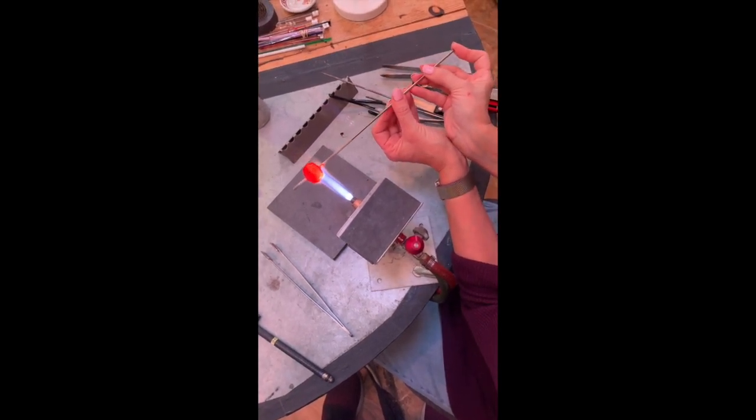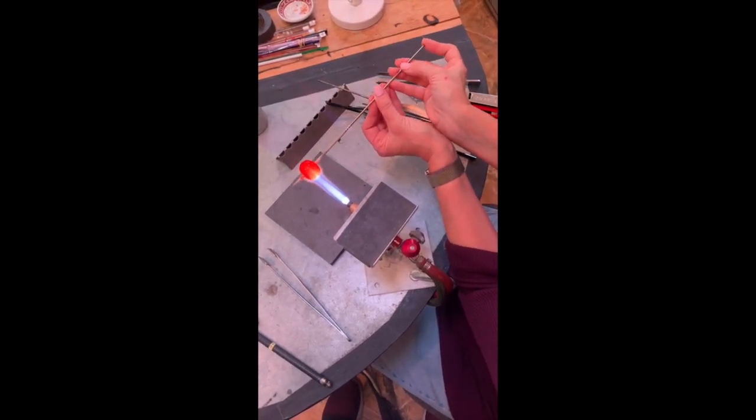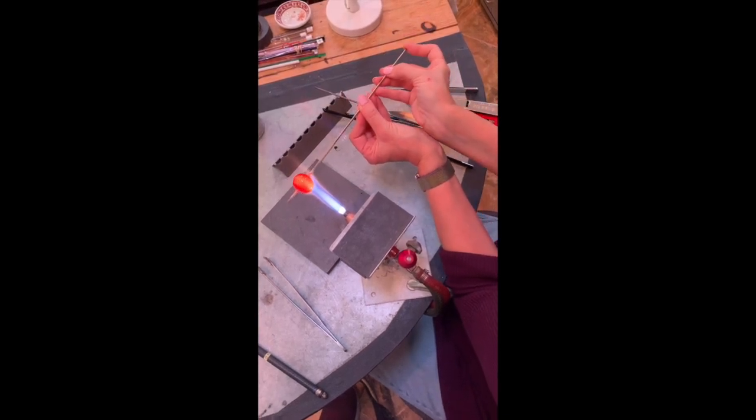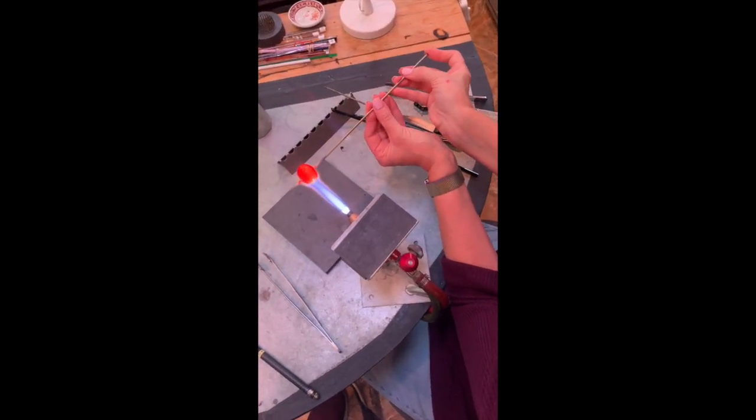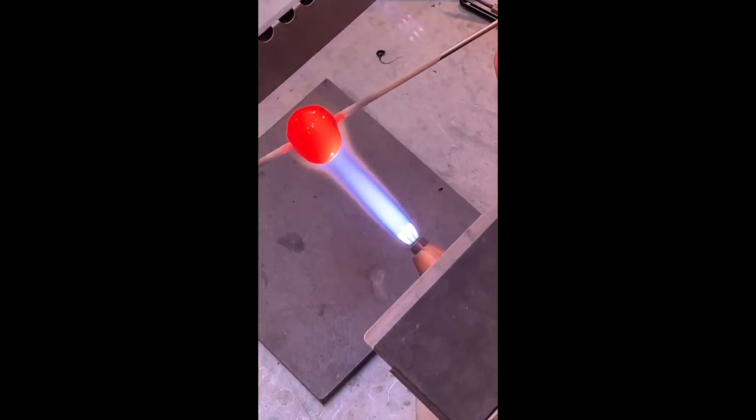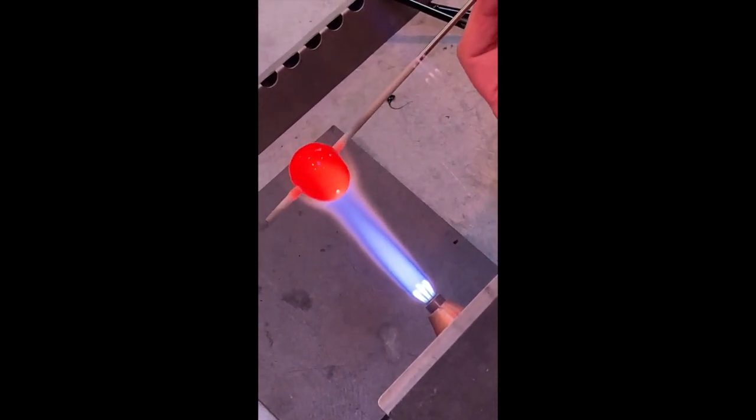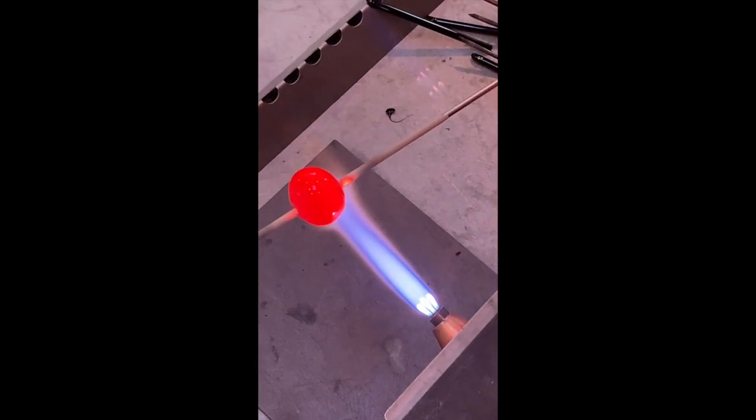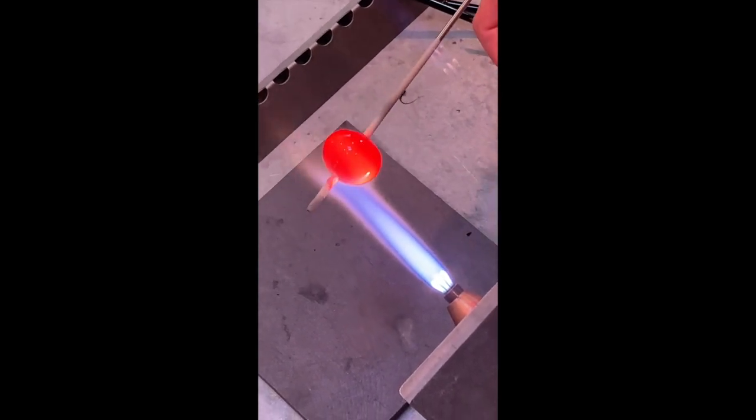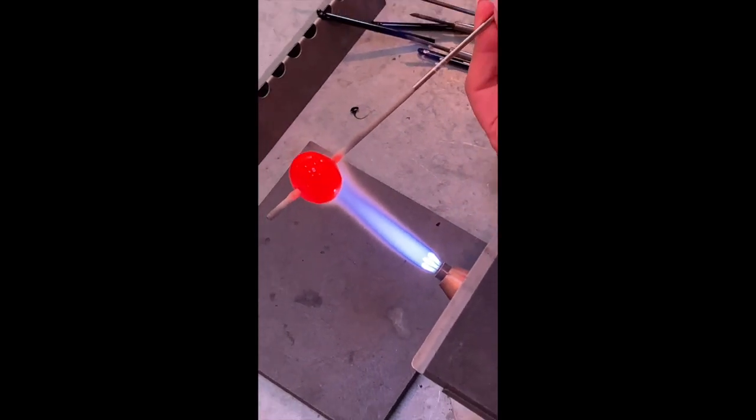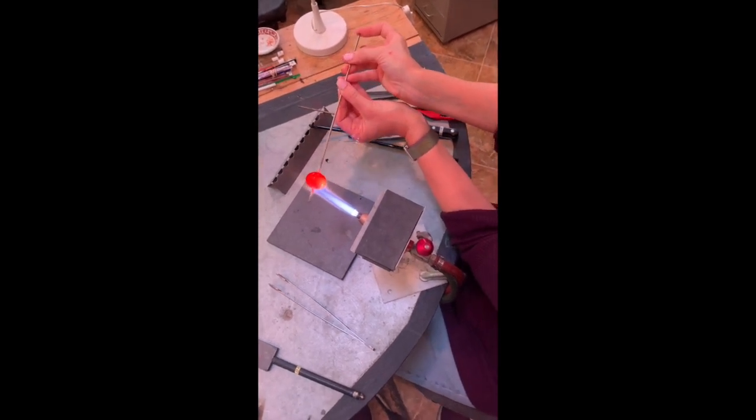pop it like a balloon. You're looking for about a 30 percent expansion, and that's a very rough number. It depends on how much glass you added, how big the bead is, how hard you blow, what kind of glass you're using. But rough rule of thumb, 20 to 30 percent. So I see an even glow in the entire bead. I'm rotating. It's a hollow bead, certainly. I'm going to bring it up to my mouth, still rotating. I'm going to move it to block the end. Sometimes I use my lip or my tongue. And then as I see the glow start to diminish, I am going to start gently blowing, and you should see the bead inflate if my cameraman does his job. So here we go.